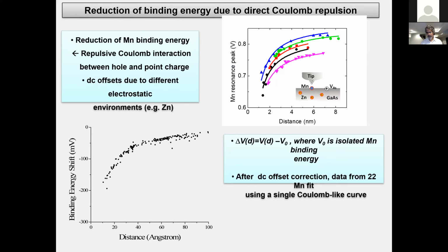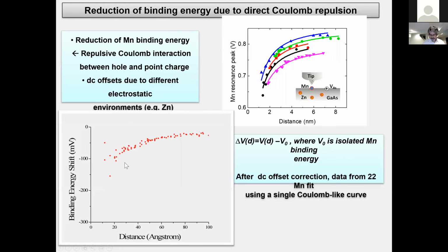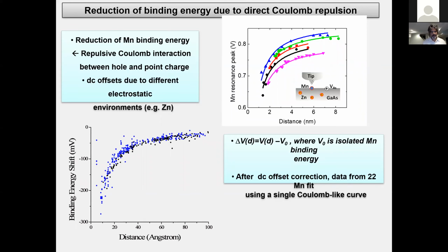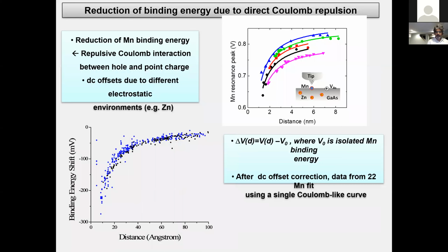And it turns out that this point charge you can realize in a few different types of systems. So for example, we've studied 3 of these. I can't get them all to display on top of each other. So the blue points are gallium atoms on top of the surface. The black points are an arsenic vacancy, and the red points here are a manganese atom on top of the surface. And it turns out all of these are +1 charged. And so you can manipulate them like a point charge to create this Coulomb effect.